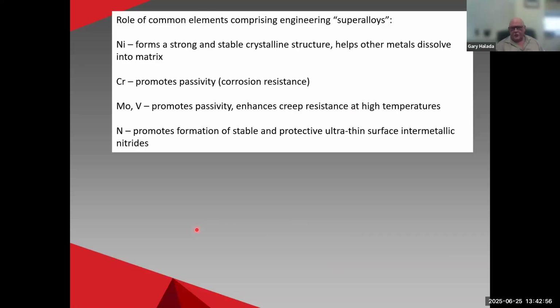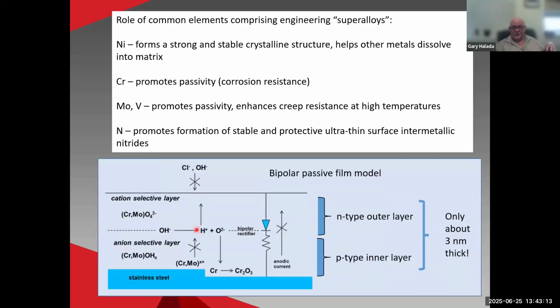A lot of materials in superalloys do protect against corrosion, or they do other things. For example, chromium, molybdenum, vanadium, these metals are added to improve the thin, passive layer that forms on the surface that's protective. Nitrogen actually forms very thin nitride layers. So I'm not going to go into this because of time, but the thin layer is only about 3 nanometers thick. That's why, by the way, the reason stainless steel looks shiny is it's covered with oxide, but the oxide's so thin that you can see through it. It's only about 3 nanometers thick. And in that layer, you form a chromium and molybdenum rich layer, for example, in certain stainless steels, that actually acts as a rectifier circuit to prevent things like chlorides and hydroxides from reacting with metal ions and causing rust.